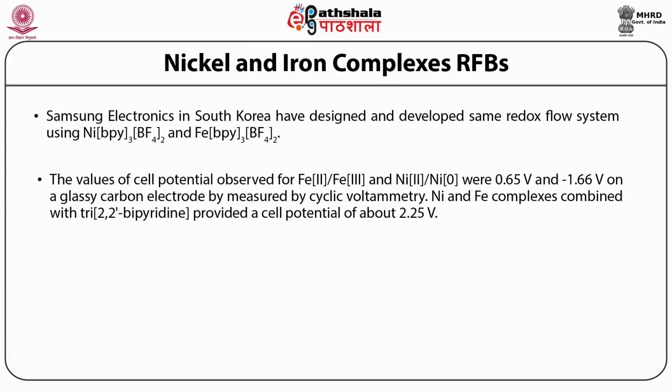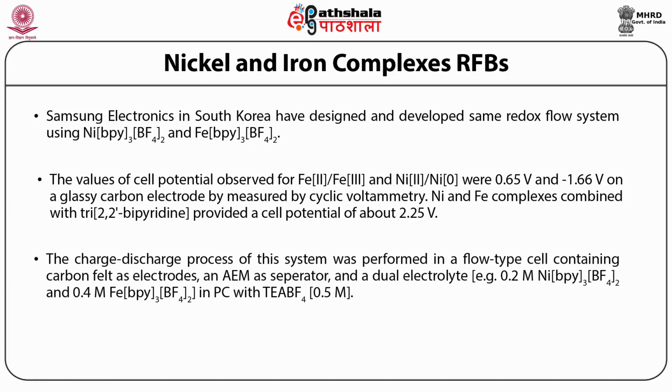Nickel and iron complexes combined with tri-2,2'-bipyridine provided a cell potential of about 2.25 volts. The charge-discharge process of this system was performed in a flow-type cell containing carbon felt as the electrodes and AEM as the separator and a dual electrolyte.